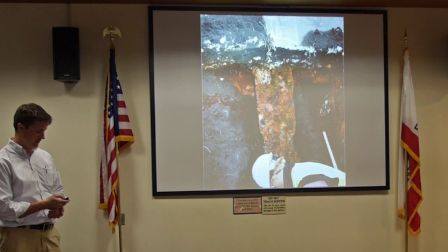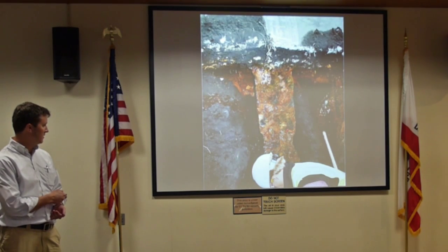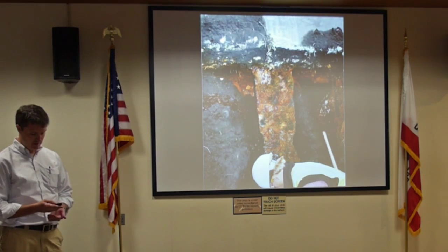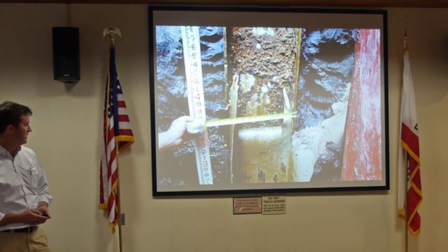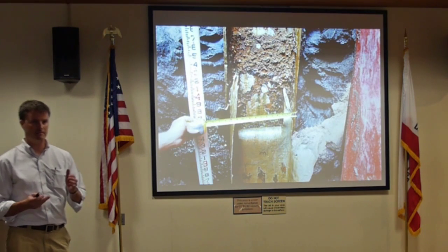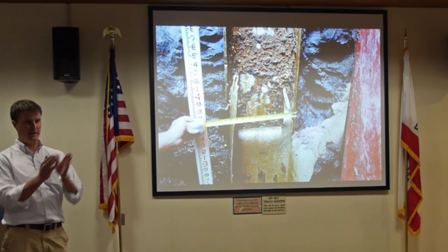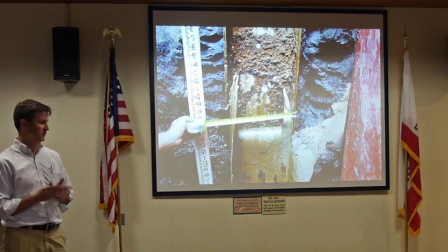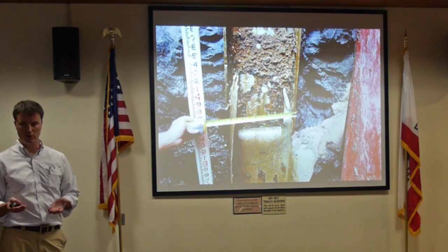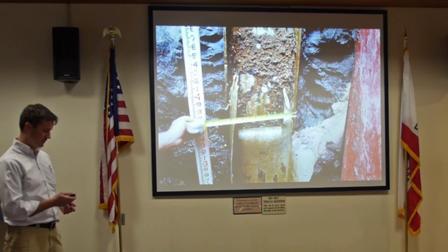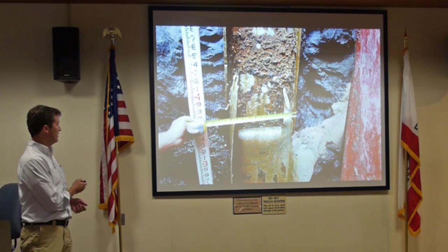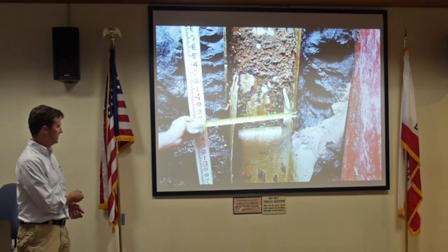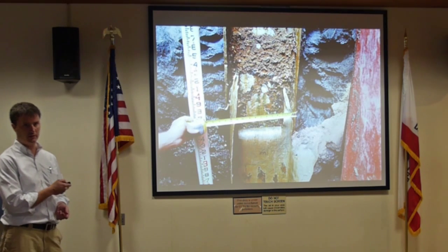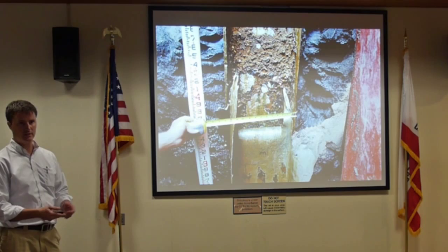You can see pretty significant necking down, the flange edges right here. And then at the portion that it failed, we actually saw that the H pile kind of moved past itself, and basically it buckled. There's enough steel section loss that it could no longer support its load. What you see here is the upper section of the pile actually moving past the lower portion in the web of the H pile, and it has basically rolled over.